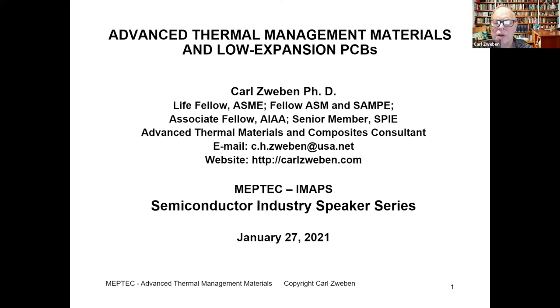Well, in most of the commercial applications that I'm familiar with, you've got a package and you attach a heat sink on top. And the heat sink is the primary method for heat transfer. And in military applications, on the other hand, it's common to use heat sinks embedded in the printed circuit board or attached to the printed circuit board. They're called thermal planes or printed circuit board heat sinks. And in that case, the heat flow goes through the heat sink or the cold plate to the edge of the printed circuit board assembly and from there into the enclosure. So there are these two different methods of heat transfer in commercial and military electronics.